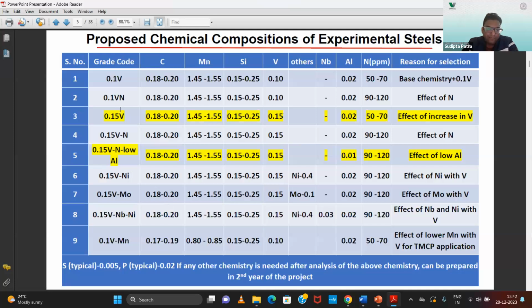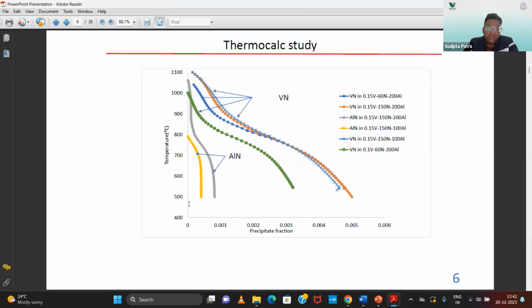So we have melted almost 4 varieties of steel out of these initially decided chemistries. And then what we observed is that if we add nitrogen, then the precipitation dissolution temperature also increases. So many precipitates are undissolved at the soaking temperature of 900 degrees centigrade. So there we will get very good grain refinement. We also observed that if we add some aluminium for deoxidation, say 0.03 to 0.04 aluminium, that will actually compete with vanadium for the nitrogen, through precipitation of aluminum nitride. So there we can also lose strength. So we have to keep the aluminum in a lower chemical composition.